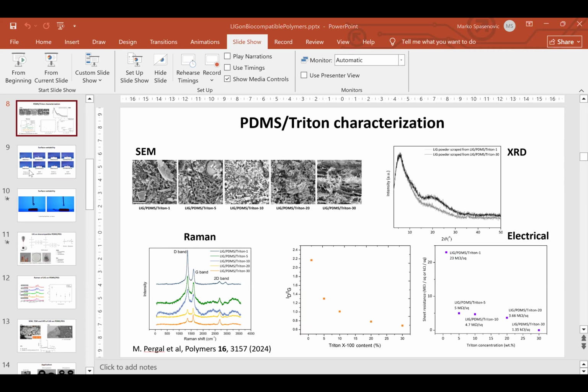Yeah, so we didn't do XRD in-house. We outsource. We go to a different institute, and they have some lookup tables, and they claim that this is okay to have it around where we see these peaks. I don't know, but indeed the defect peak shown here is quite high, and especially when you add just a little bit of Triton. So I don't know if you still see the slides that I'm sharing, but the top curve is just 1% Triton, and that has a very high D-band.